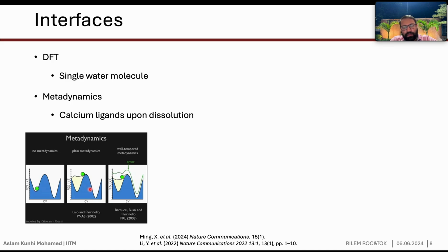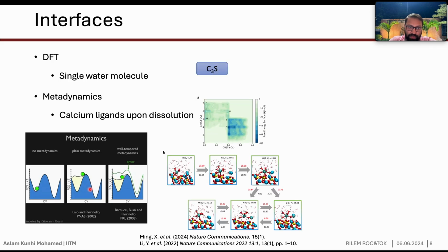Now, people have also used DFT, where you can look at single water molecule adsorption on the C3S surface. Also recently some papers have come out where people have looked at how the coordination of calcium and the ligands change upon dissolution, similar to the work I described in the previous slide. Here they have used metadynamics, which is an enhanced sampling technique. It will accelerate certain rare events against a coordination collective variable. Here is the coordination of calcium with water and calcium with the oxygen of the silicates.